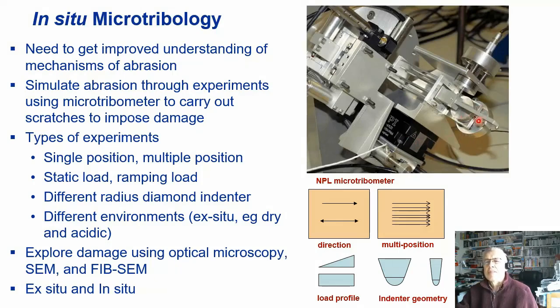And the other one measures the lateral deflection of the probe, which gives a measure of friction. So you can carry out lots of different experiments with this. Most of these simulate abrasion using single point abrasion, but you can use single positions, multiple positions, static load, ramping load, different diamond radii, different environments.